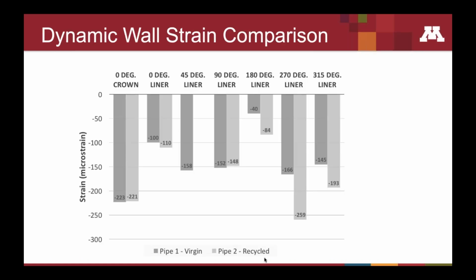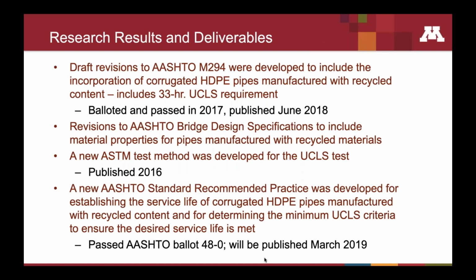And what we found is virtually no difference between the pipe manufactured with virgin material in the dark gray bars here versus the pipe manufactured with recycled material. They performed pretty much identically throughout the entire duration of the test. And we found that there was no difference in performance. So out of this, we were able to draft some revisions to the AASHTO specification to include recycled materials.